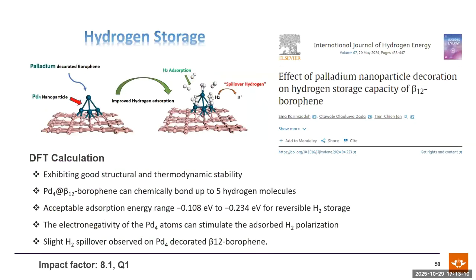This is another work in the International Journal of Hydrogen Energy, on the effect of palladium nanoparticle decoration on the hydrogen storage capacity of beta-12 borophene. This also shows very good results. They can bond up to 5 hydrogen molecules, and the adsorption energy ranges from minus 0.108 eV to minus 0.234 eV, acceptable for reversible hydrogen storage. I think this is pretty much in line with the DOE target.